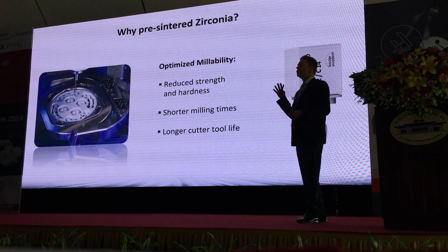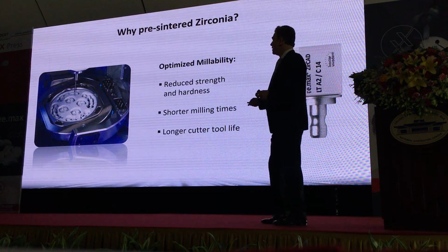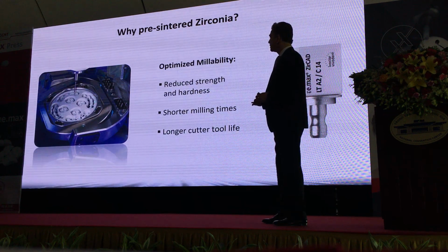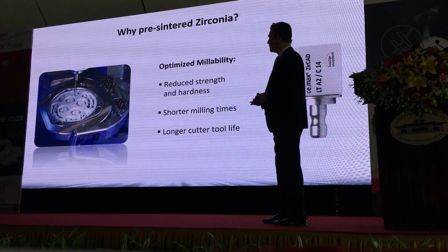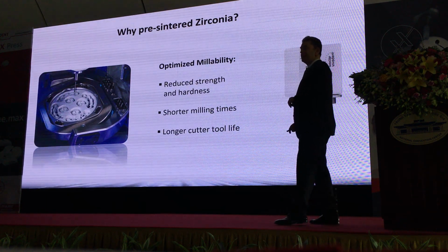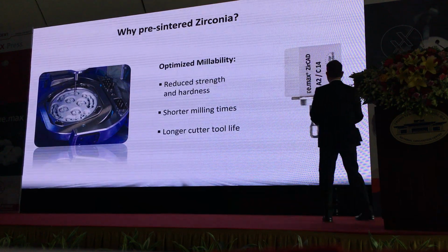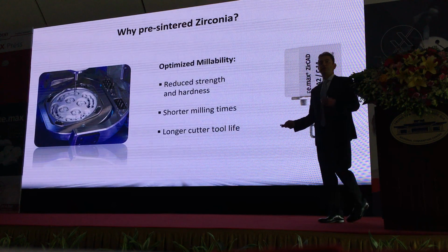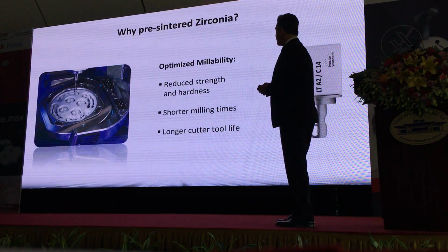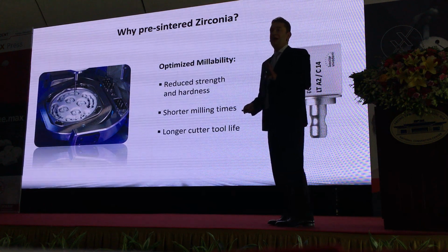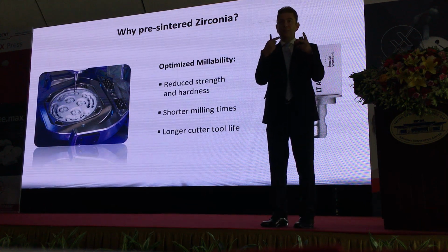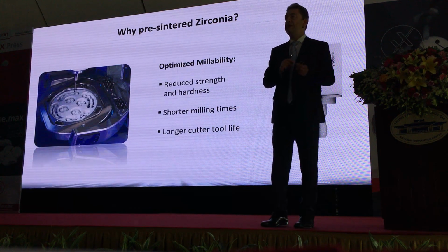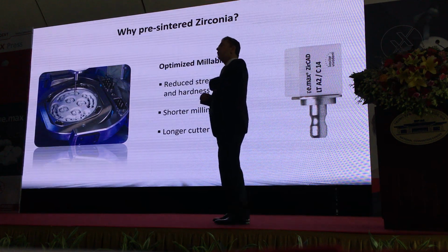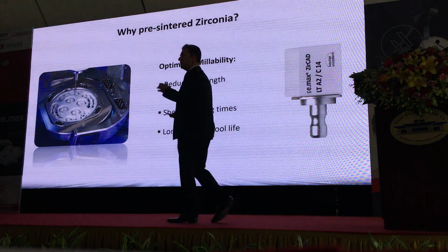Okay, so zirconia can be processed usually in the lab. The lab technician is usually using discs, and the restoration is milled from the disc. And of course now for chairside CAD/CAM dentists, this material is also available as a block. We can put it into a CEREC system, for example. But you can see this material does not have yet the final strength, because if we have a strong material, we cannot mill it easily. So we need to have it in a pre-sintered stage. So it's not so strong yet, so we can easily mill it. And then later on, we need to sinter it in a special furnace at a very high temperature to have the final strength of the restoration.